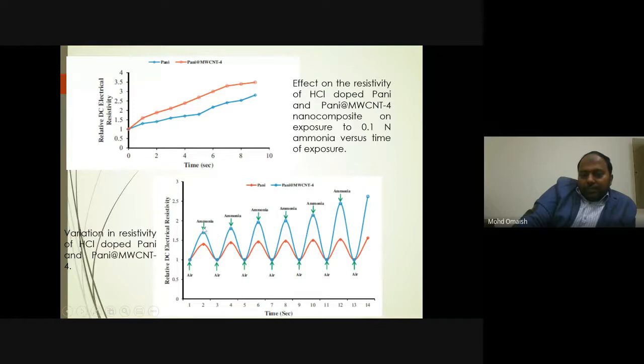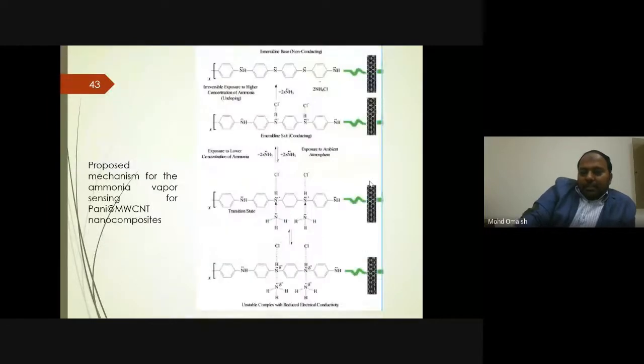We got a large decrease in the electrical conductivity when we exposed it to ammonia, and after that the electrical conductivity was restored in air. We checked for multiple cycles, 10-15 cycles, and we got good promising results. But this was one of the steps towards making very good sensors. And this is the mechanism of the gas sensing.